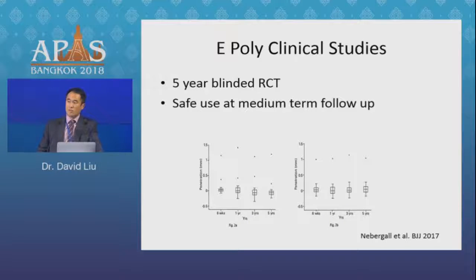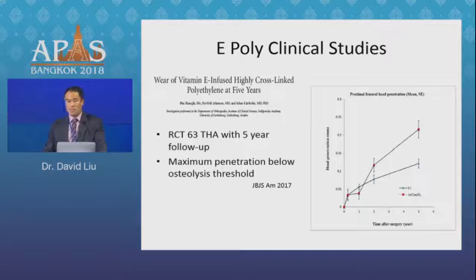Both studies have done RSA wear rates, and the head penetration rates are similar, if not perhaps a little better than conventional cross-linked polyethylene, which is pleasing. And even more pleasing, it appears that the head penetration rate per year is below that osteolysis threshold described by Engh of 0.1 millimetre per year. So out to 5 years, we do appear to have fairly promising results, but still very preliminary.